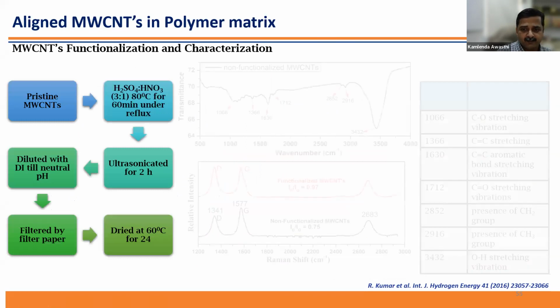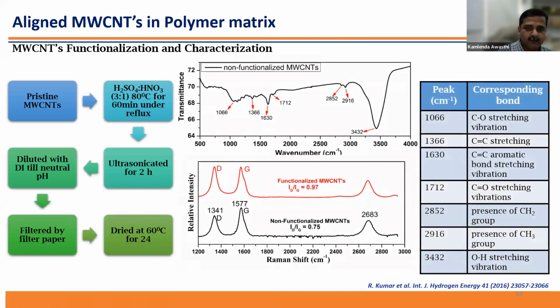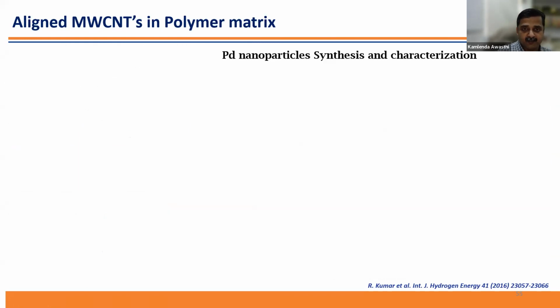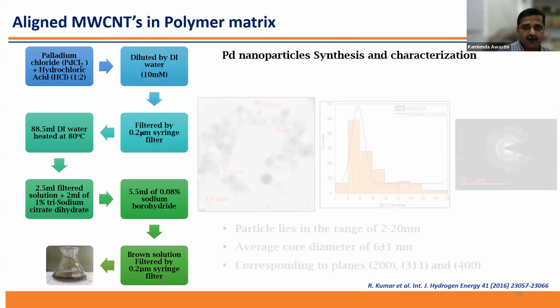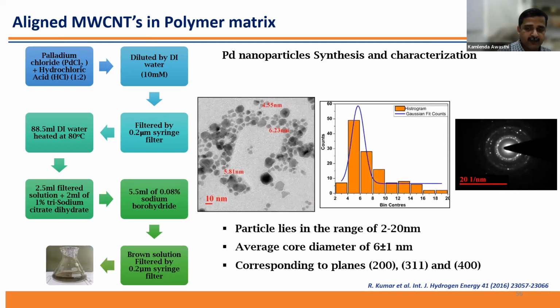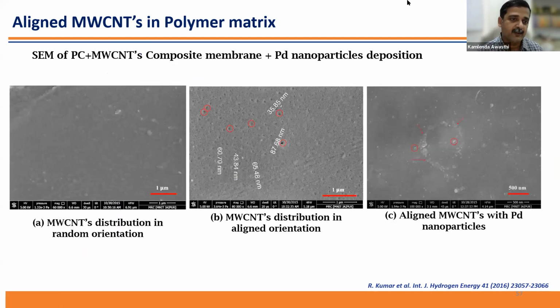Okay, and this is some primary measurement that confirmed that carbon nanotubes are there. Then we used palladium nanoparticle synthesis, and we used these palladium nanoparticles in the CNTs. Because of this palladium, we had very good absorption of hydrogen, with other gases going out. This way we can make a selective membrane by using this nanocomposite. Here you can see these pits marked with a circle. Basically, these are the openings of your nanotubes over the surface.